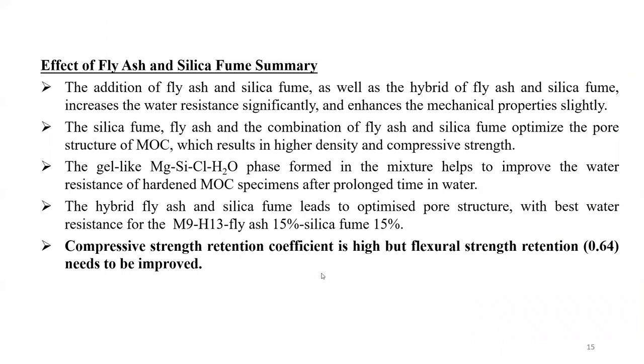Before we continue, just to give a summary of the effect of fly ash and silica fume. The addition of fly ash and silica fume, as well as the hybrid of fly ash and silica fume, increases the water resistance significantly and enhances the mechanical properties slightly. The silica fume, fly ash, and the combination of fly ash and silica fume optimize the pore structure of MOC, which results in higher density and compressive strength.